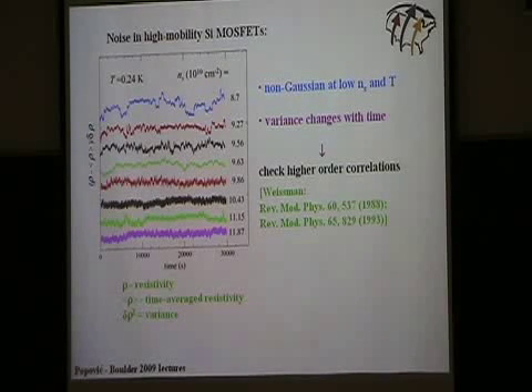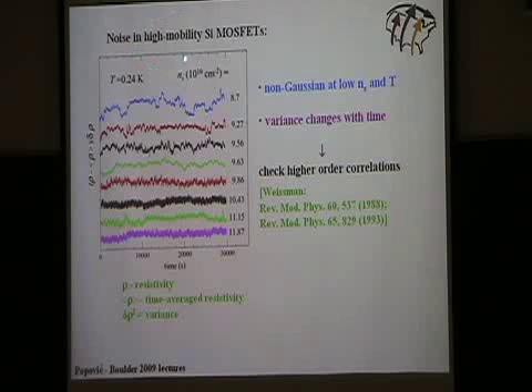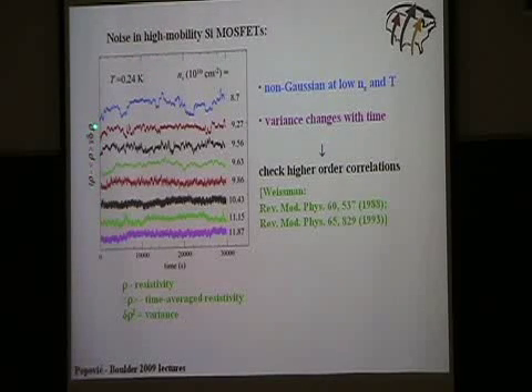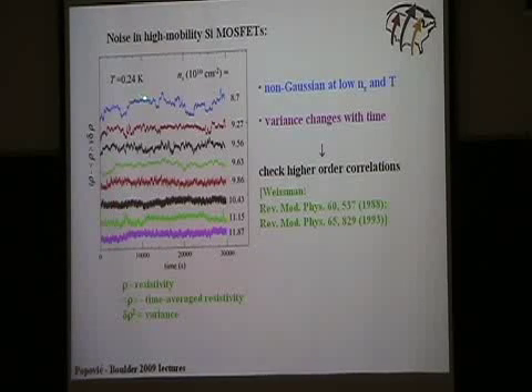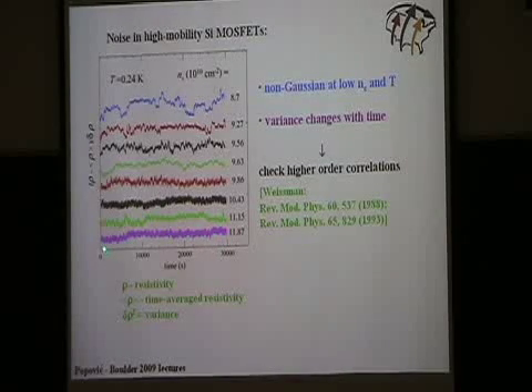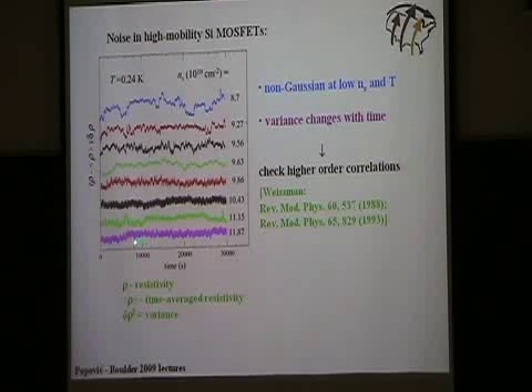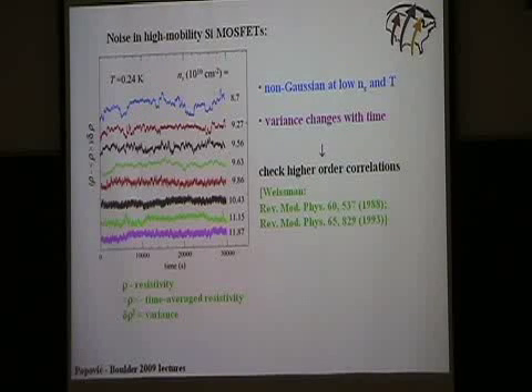Now we want to look at the non-Gaussianity in a little more detail, and here are again a few traces obtained on high mobility samples. Here we are dividing by the standard deviation so that these are more or less the same on this scale. The reason for that is we want to focus on the shape of the noise. You can see now clearly that at the high densities the noise is Gaussian. And then as you reduce the density, it becomes non-Gaussian. You start seeing slower modulations on top of the rapid ones.